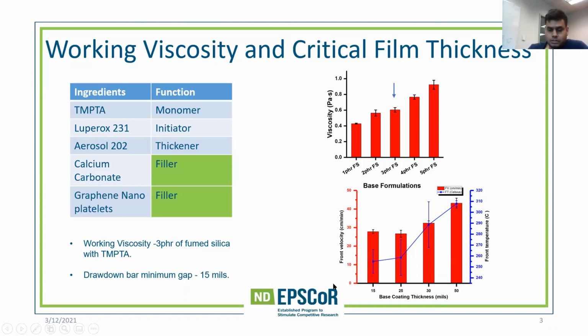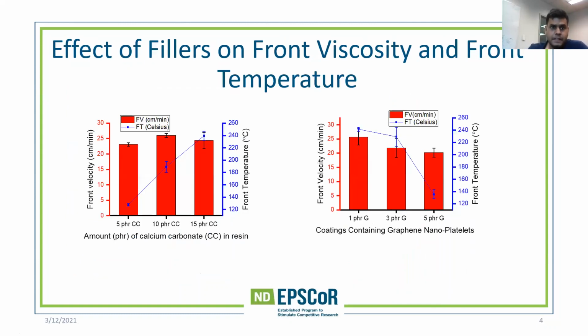When we started making coatings and doing the frontal polymerization heated with a heat gun, we found out that 15 mils is the minimum gap in the drawdown bar required for the front to propagate neatly and cleanly. If this gap in the drawdown bar with which we are making films is less than 15 mils, then the front doesn't propagate. The material is not enough, or there is not enough heat generated, which can further polymerize the monomers.